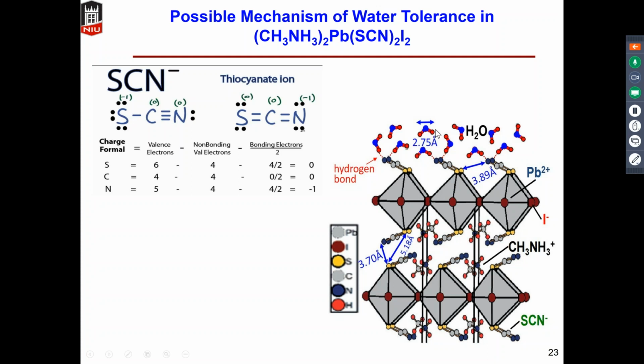And so we can use this crystal structure of the pseudo-halide-based perovskite to explain why it becomes more water tolerant. The pseudo-halide SCN is attached to the lead with the dangling atom of nitrogen here, and the nitrogen can form a strong hydrogen bond with incoming water molecules. And because the opening here is just a few water molecules wide, when this water molecule binds